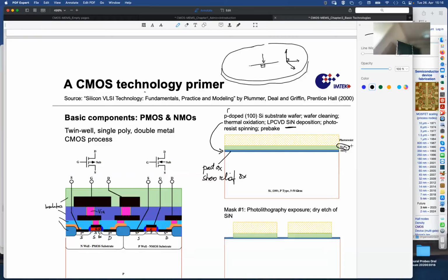And after this thermal oxidation at maybe 900 degrees for not too long a time, the wafer goes into another furnace where some ammonia and some dichlorosilane flows through at high temperature, 900 degrees, and then by decomposition of these gases and recombination of their constituents, there grows a silicon nitride layer. So we have grown a silicon oxide by consuming some silicon with oxygen, made a little oxide layer, and now we grow through this silicon nitride layer. And these are processes that are, as I said, at reasonably high temperatures.